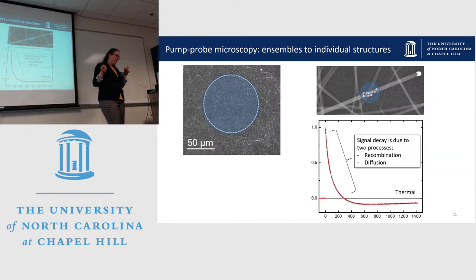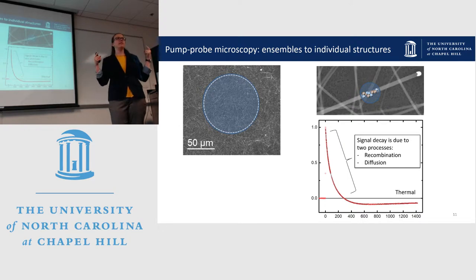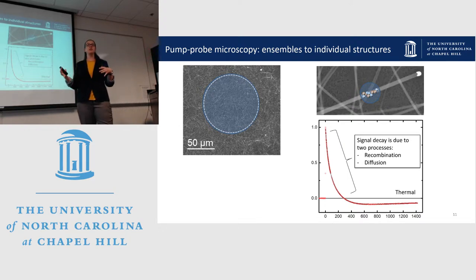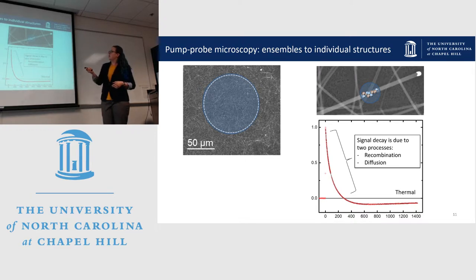So how can we actually use this to get a lifetime? Well, if we were looking at just transient absorption spectroscopy, so not in a microscopy mode, it's actually really straightforward. Your beam covers the entirety of, again, thousands of nanowires, and so your entire signal decay just comes from recombination. You can fit it to a single exponential, and you're done. Easy.